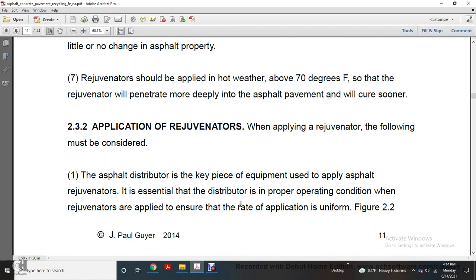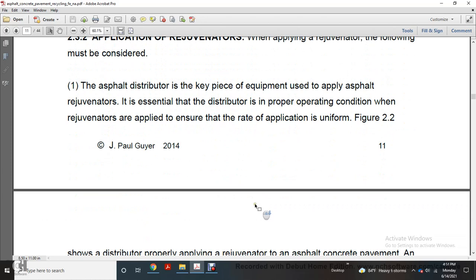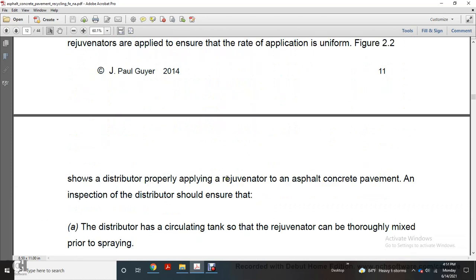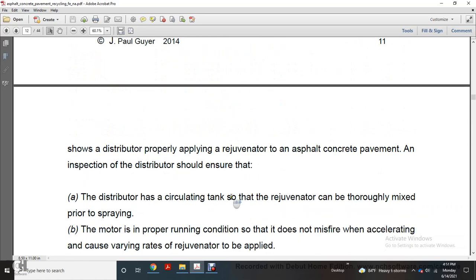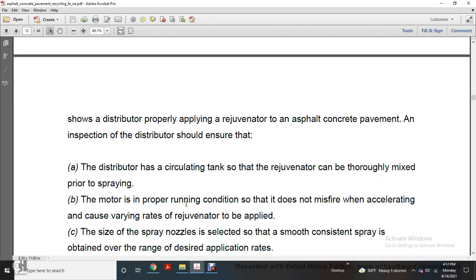When rejuvenator is applied, ensure the rate of application is uniform (Figure 2-2). Show the distributor properly applying the rejuvenator on asphalt concrete pavement. Inspection of the distributor should ensure that the distributor circulating tank is working so that the rejuvenator can thoroughly mix prior to spraying, and that the motor is in proper running condition so that it does not misfire, when accelerating and cause varying rates of rejuvenator to be applied.